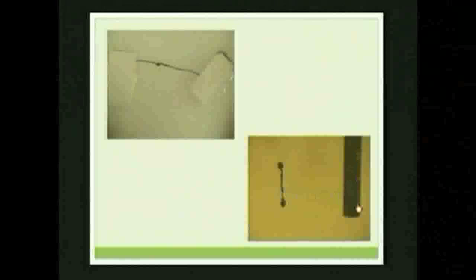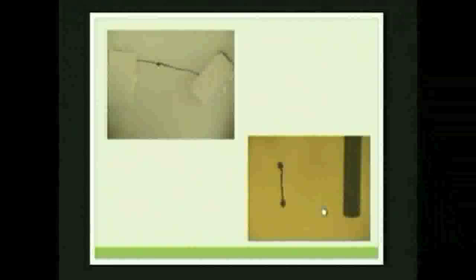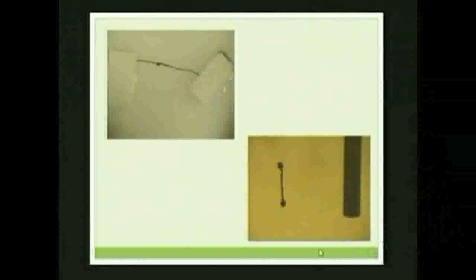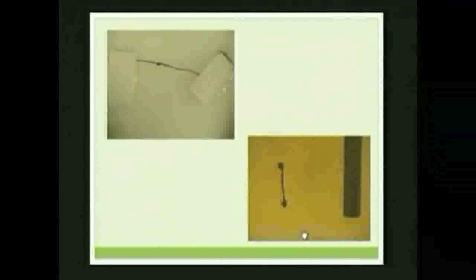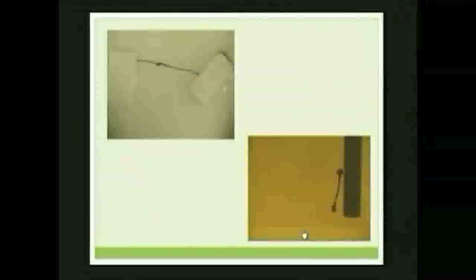And the other funny movie, here you have the fiber. The fiber is attached to an electrode here, and here you have another electrode. And we induce heating of this fiber by Joule effect. There is a current going through the fiber. At the first moment you don't see anything, and then, clack, you see the very strong contraction of the fiber. So the force seems to be interesting, the stress recovery.